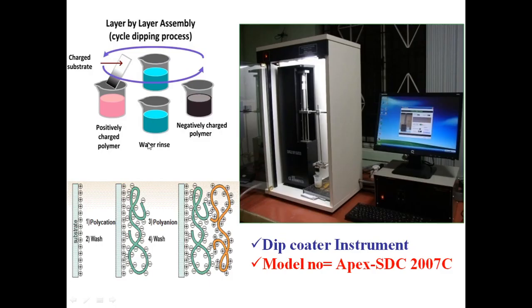The layer by layer self-assembly technique is also quite an easy technique using this automatic control dip coater unit. First of all, the solid substrate is dipped into a solution of a positively charged polymer or other material, then it is rinsed in pure deionized water to wash off the excess positively charged particles. Then again it is dipped into the solution of the negatively charged material, and again it is taken out and washed in water. Thus, a bilayer of anionic and cationic materials is prepared. Thus, an LBL film is formed, and it can be prepared automatically using this dip coating instrument.